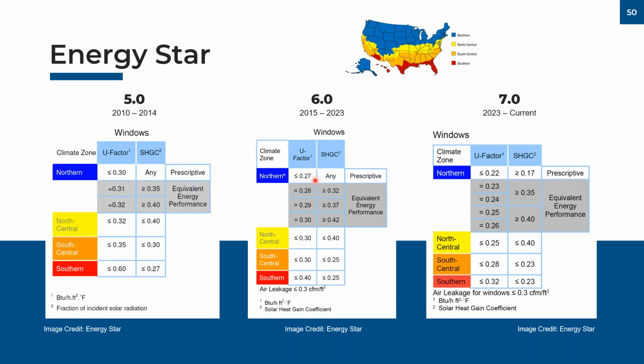Then with version 6.0, we saw Energy Star creep up to 0.27, and now from a prescriptive standpoint, it's all the way up to 0.22. And this is really marking a point in history where once we go beyond 0.25, 0.24, this is really the point at which dual pane windows top out in what they can really achieve for performance. So as we look at higher performing window systems, 0.23, 0.22, this is really the tipping point where we need to go from dual pane to triple pane windows.